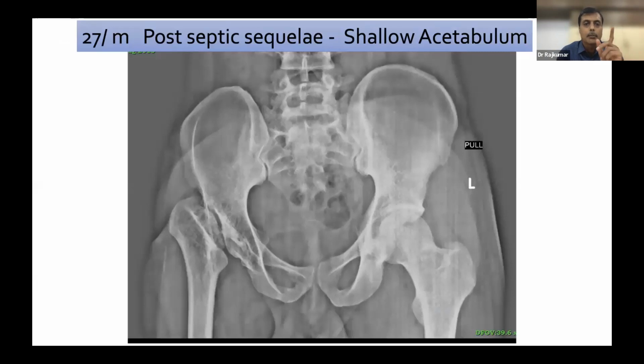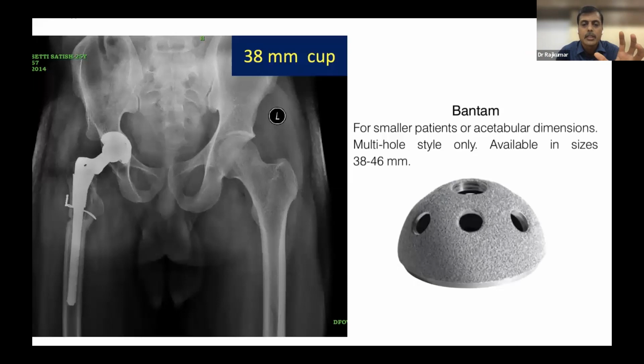So here, what is that? A post-septic sequela, a very shallow acetabulum. Already, you can see there is no acetabulum at all. So in this situation, after you template, you need to know where you are going to place the cup, how you are going to achieve the stability. Here I have used the smallest cup, with a little high hip center. What is that smallest cup? In DePuy, you call it the bantam cups, where the sizes start from 38 to 46. The most important thing is 38, 40, 42. These three cups will take only a 22.2 mm head. So that also you should know.